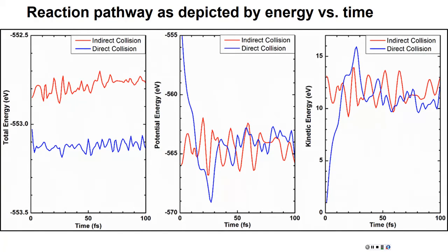Another interesting thing is that if you plot energy as a function of time during the molecular dynamics simulations, what you notice is that there's this huge drop, I should say, in potential energy, or increase in kinetic energy, for the direct collision. Intuitively, you would think this may correspond to either a bond forming, breaking, or some reorientation of the molecule being a kinetic barrier. However, at these time points, there are no ionic positions or atomic positions that can be related to forming bonds or breaking bonds.